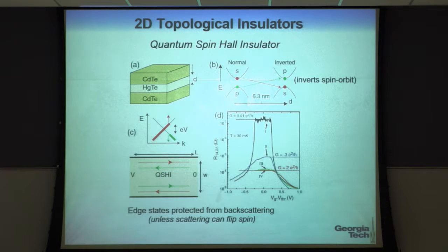So at the edges, you find modes where, in fact, due to the spin-orbit coupling, so I didn't mention, but when you invert these states, it also inverts the sense of the spin-orbit coupling. And what does spin-orbit coupling do? Well, it couples spin to orbit. It couples k to the spin direction, okay? And so the net result is that these edge states, if they're propagating in this direction, then they're spin up. If they're propagating in this direction on this edge, then they're spin down.